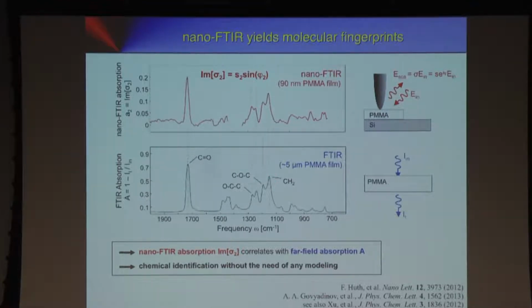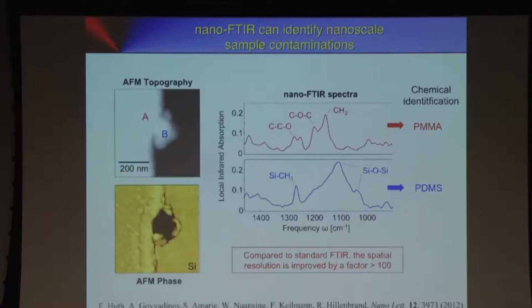This is for some people surprising, for other people it's totally normal. This is because we have the phase, and phase always stands for a resonant absorption process. And this is why we have direct access to absorption. So that was then on the same sample, we found this particle. That's an atomic force microscopy image. That's the height. We see here a layer, and here we see a particle sticking out.